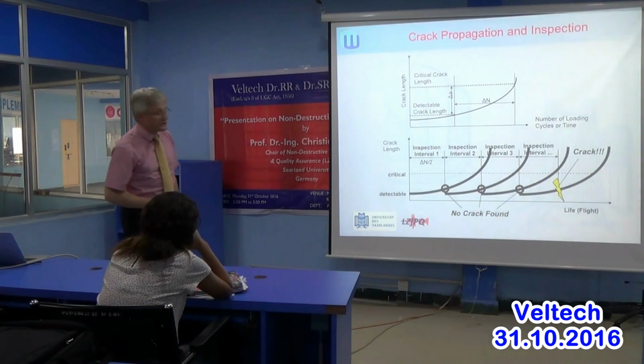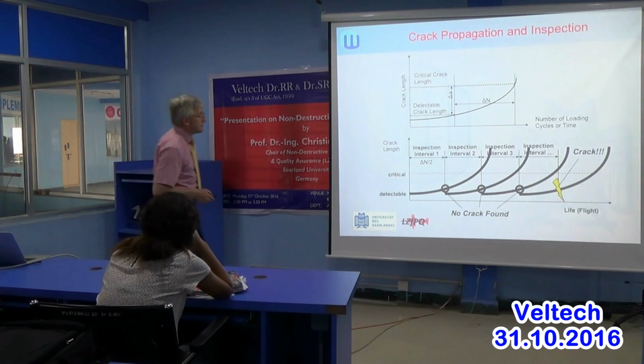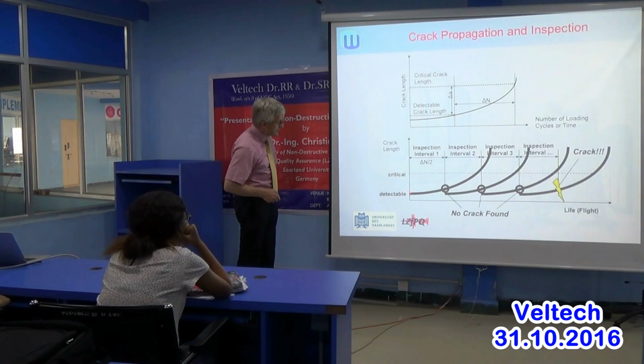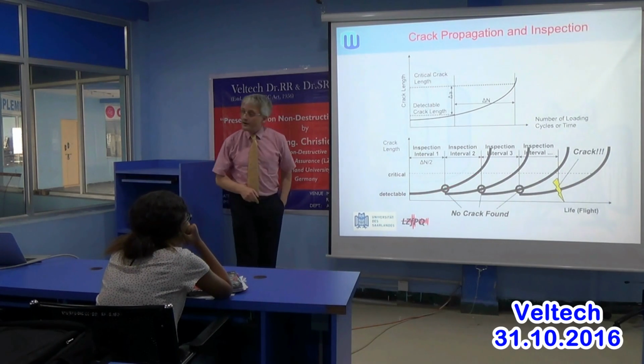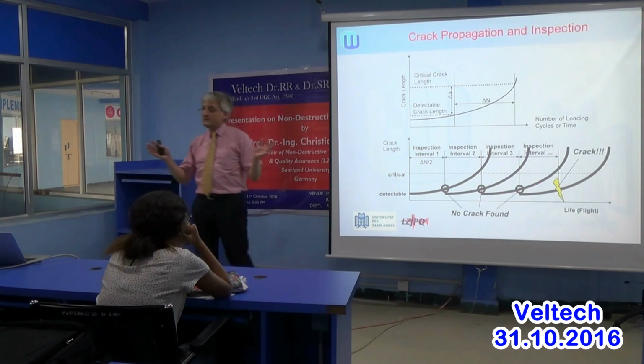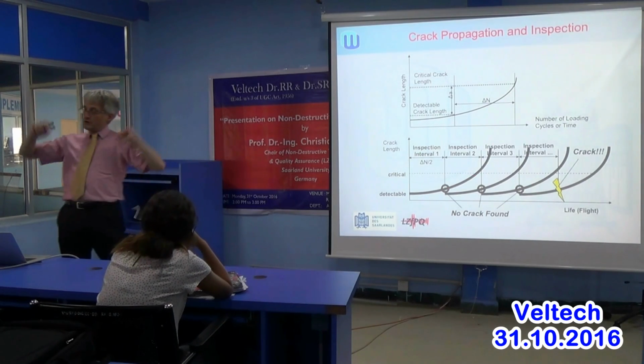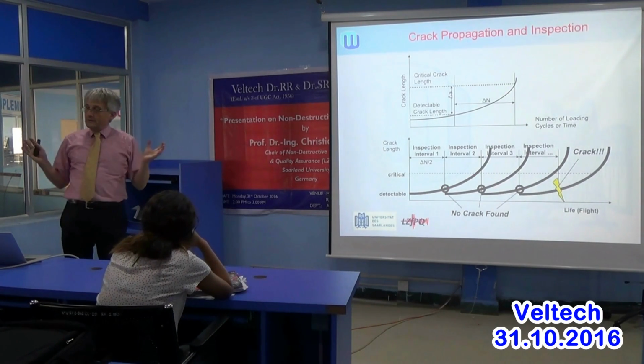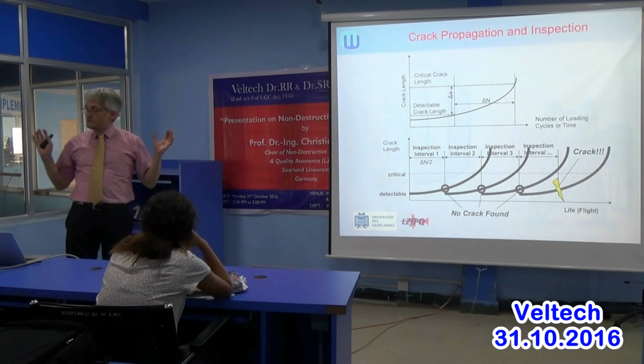So we get a procedure which looks like this one here. So that's the same as up here. That's the detectable crack length. No, this is the critical crack length, sorry. And this is half of that life. And we inspect. We inspect at the locations which are critical. And we don't see a crack.